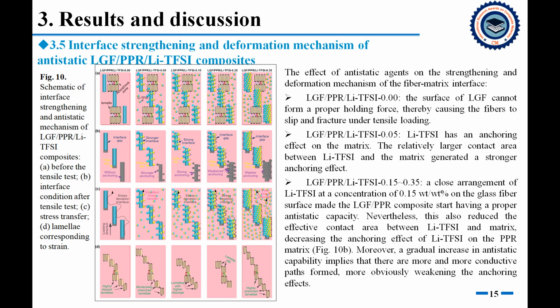Integrating crystallization behavior, crystal structure, mechanical properties, and failure mechanism, we draw a schematic diagram of the interface strengthening and antistatic mechanism. First, without organic salt, the surface of the long glass fiber cannot form a proper holding force, thereby causing the fibers to slip and fracture under the tensile loading.